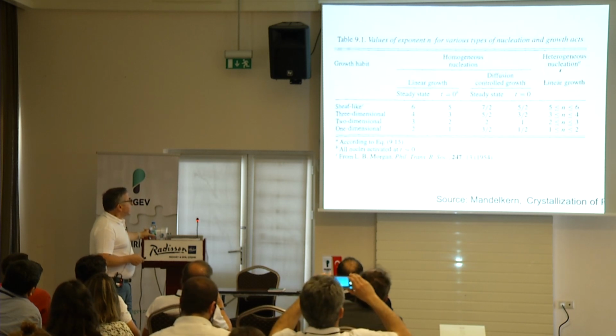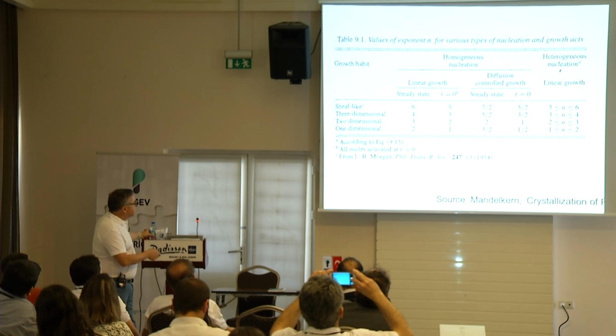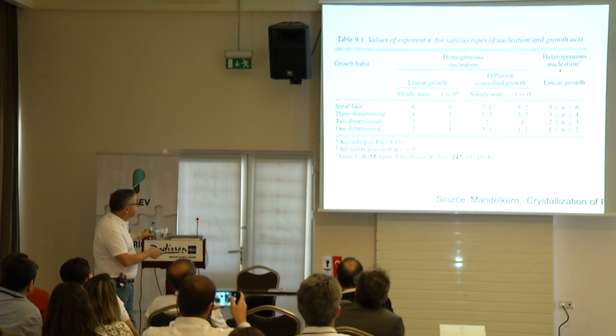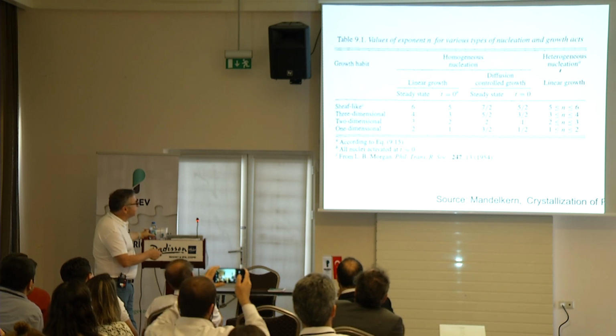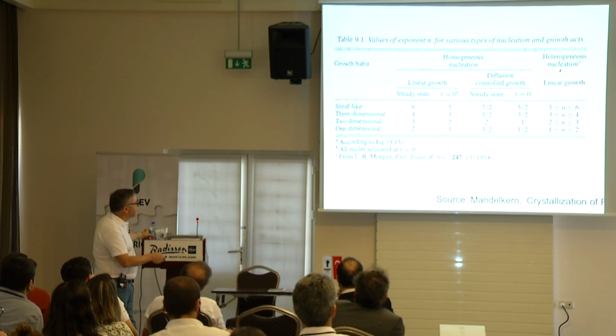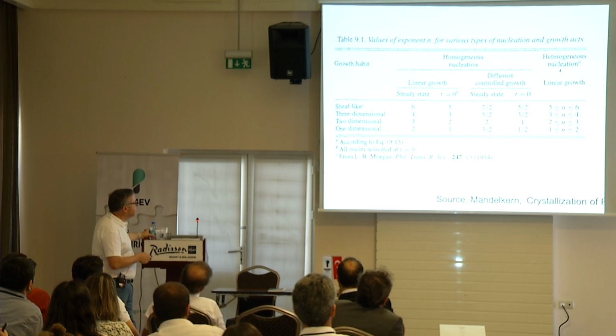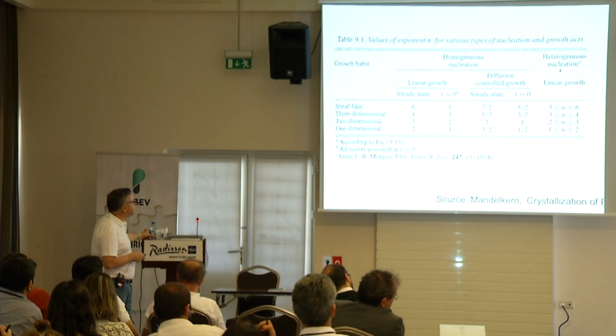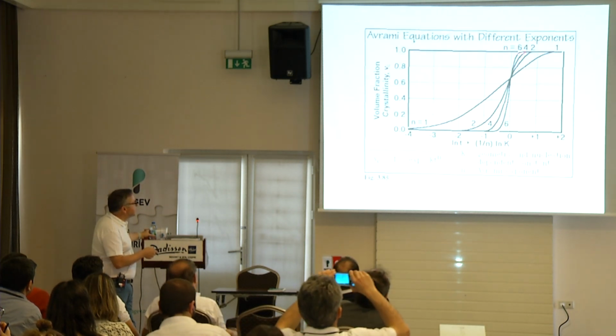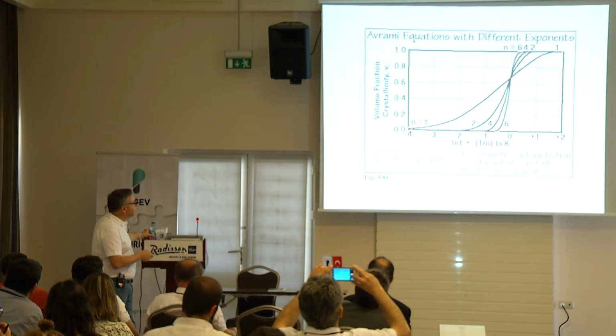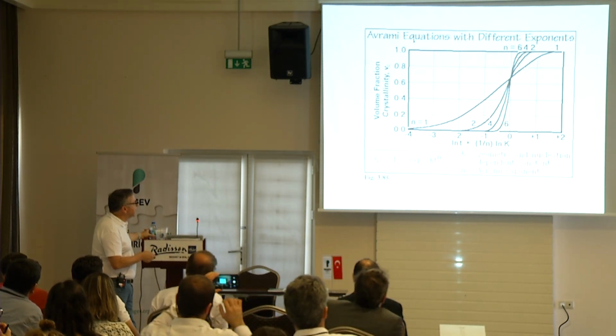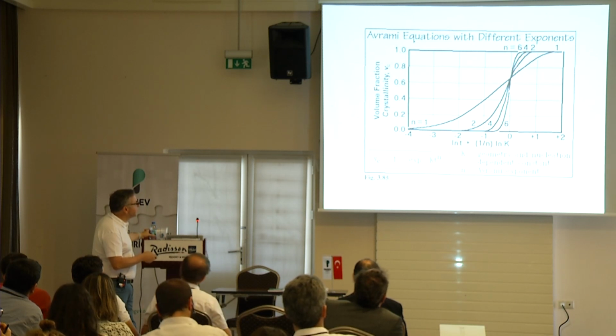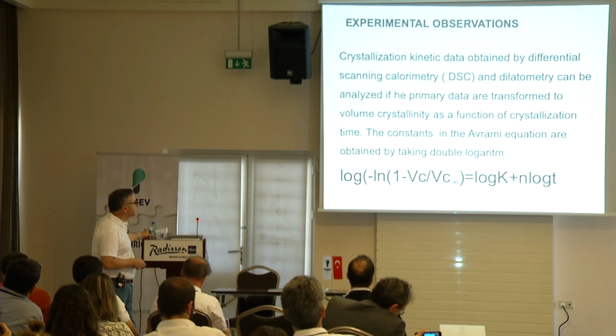All right. So the kind of numbers are here. One-dimensional is n equal to 2, two-dimensional is 3, three-dimensional is 4, and sheaf-like is 6, and there are other regions that I'm not covering. Heterogeneous also changes. You just simply measure these, and there are tables that you can get from nice books like Mandelkern's Crystallization of Polymers that you can follow. Typical n changes: these are theoretical curves. The gradual change is given with 1, and a much sharper change is n equal to 6, from the crystallization kinetics curve for the Avrami equation.